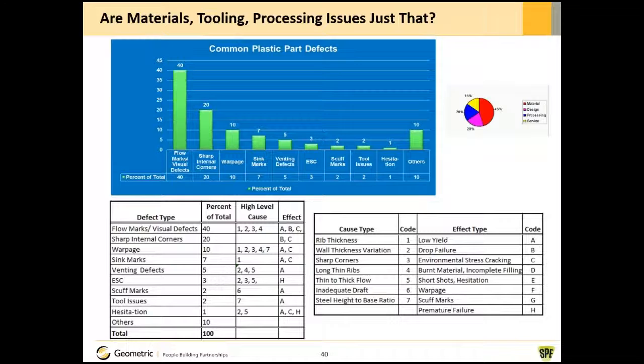That's very, very wrong. If you look at the causes, they're designated as 1, 2, 3, 4, and we move to this table on the left. 1 is rib thickness, 2 is wall thickness variation, 3 is sharp corners, 4 is long, thin ribs. All of these combine to cause these flow marks and visual defects.